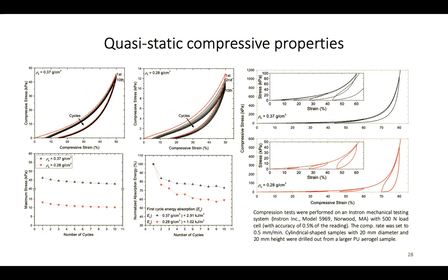Two different scenarios have been experimented. In the first scenario, we compress the sample all the way to 50%, and then the platen comes back to its original position. That's why we see a decent recovery for the sample.